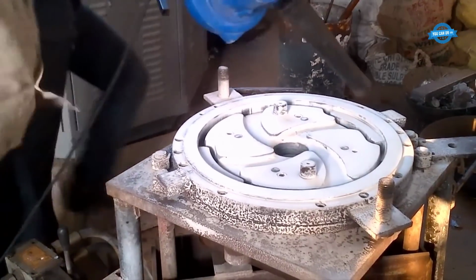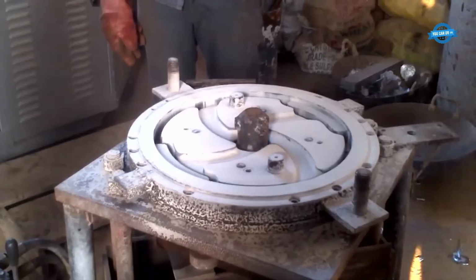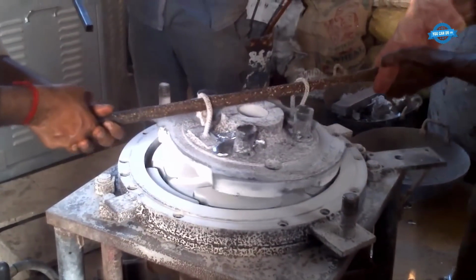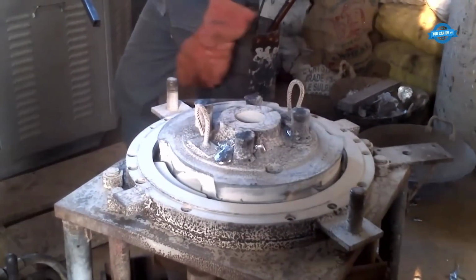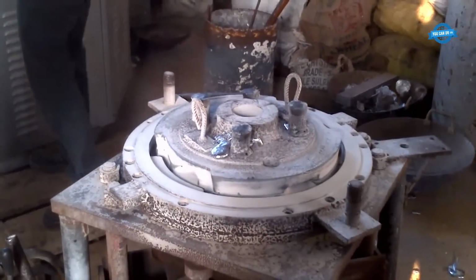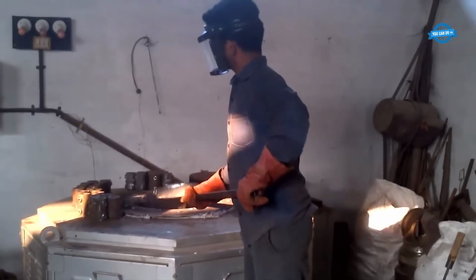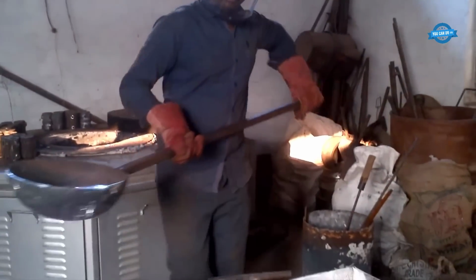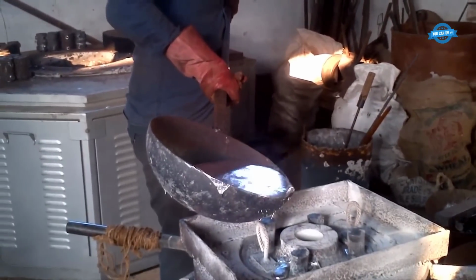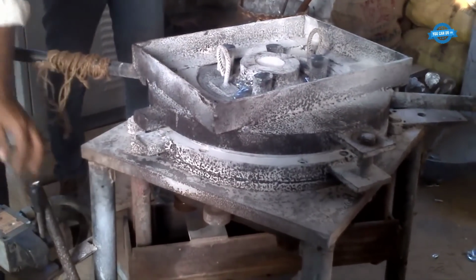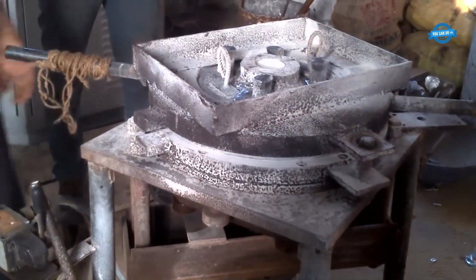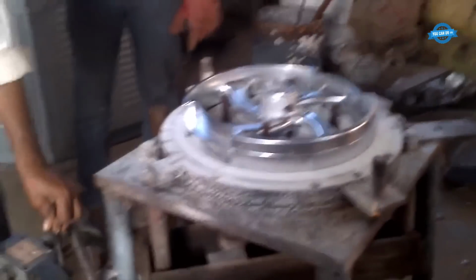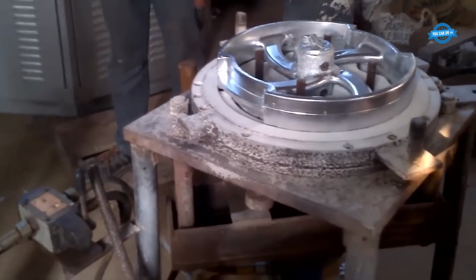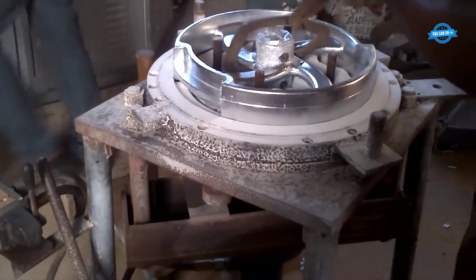Aluminium alloy wheels are crafted through a permanent mold casting process, where molten aluminium alloy is poured into a reusable steel mold. The alloy, typically a blend of aluminium, silicon, and magnesium, is heated to around 700 degrees Celsius before being gravity-fed or pressure-injected into the mold. The mold's design ensures precise wheel shapes and enhances strength. After cooling and solidifying, the casting is removed, trimmed, and heat-treated to improve durability. Finally, the wheels undergo machining and finishing for a polished look.